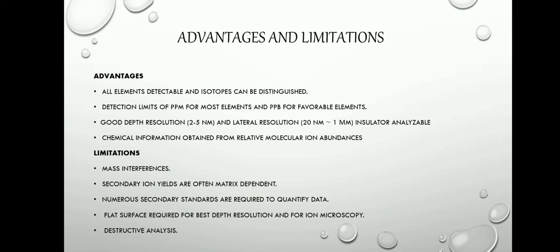About limitations: mass interferences; secondary ion yields are often matrix dependent; numerous secondary standards are required to quantify data; flat surfaces required for best depth resolution and for ion microscopy; destructive analysis.